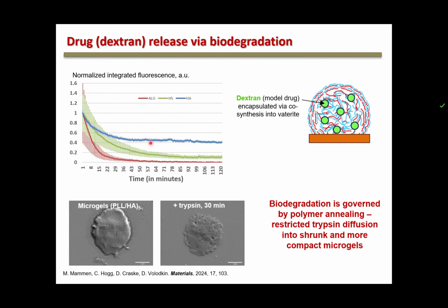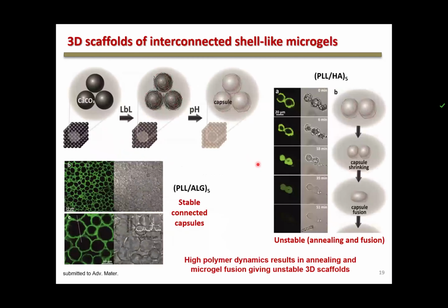They degrade much less. So this again may be explained by our mechanism of shrinkage and mechanism of annealing, that if they shrink more, there is less pores in the system, they are more compact, and then it is more hard for enzyme to go through this system and to cut into pieces the polymers and induce biodegradation. So this is in line with our mechanism.